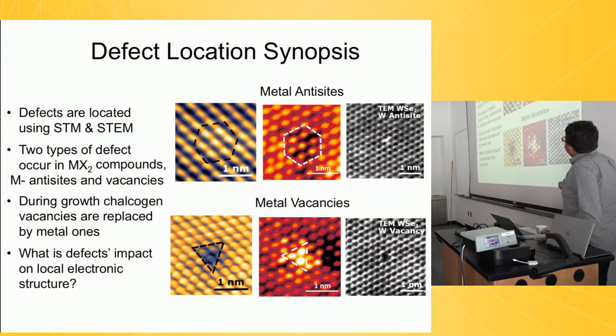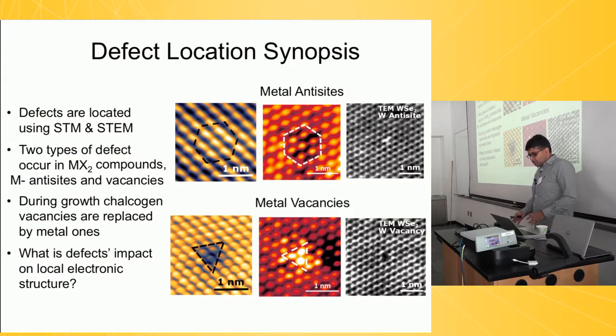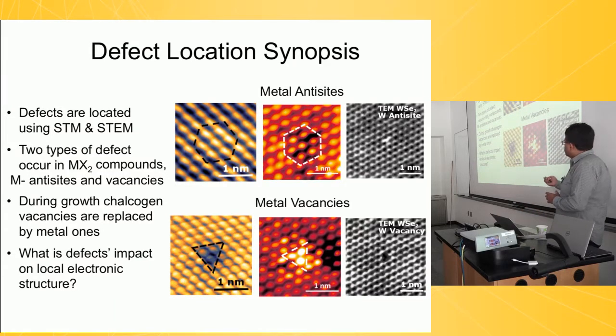Good. Okay, so here's a summary of this part. What we see primarily are two defect types. One is the metal vacancy, one is the metal anti-site. Depending upon the growth method, the numbers of these don't necessarily have to be one-to-one. In our very best crystals, we have only this type of defect. And as the defect quantity gets higher, we see more and more of the anti-sites.